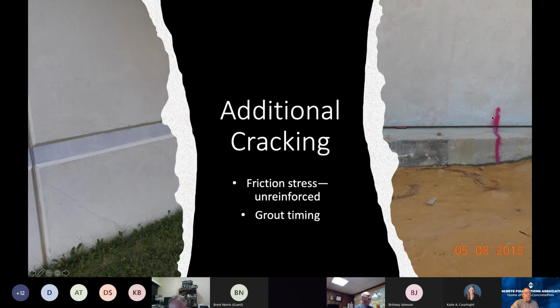We talked about additional cracking. So we showed this condition earlier, the load cracking on the footing, and the problem with those oftentimes is once the footing cracks like that, the footing can begin to rotate. If there's any kind of differential stress on the soils or differential pressure on soil capacities themselves, those footings can begin to rotate or begin to shift, and you can open up panel joints. I saw that on a freezer facility several years ago where the contractor had cracked the footing because of the shim stacks and didn't grout soon enough. It went unnoticed until the freezer was operational, and they started getting huge ice dams opening up in the upper sections of the panel joints, and it was because they got rotation in the footing because of the amount of cracking that occurred from the loads of those panels.